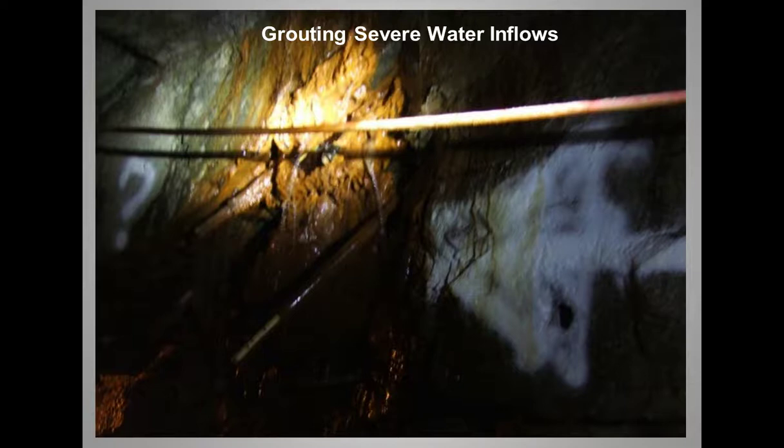Not all tunnels and tunnel leaks are solved quickly. This is an example of a hard rock tunnel with severe water inflow problems. Large jack leg drills and mechanical injection packers were utilized on this project to pump large volumes of polyurethane resin and to seal the large inflows. What tunnel crews had spent weeks on injecting thousands of bags of Portland cement took only one shift with polyurethane resin.